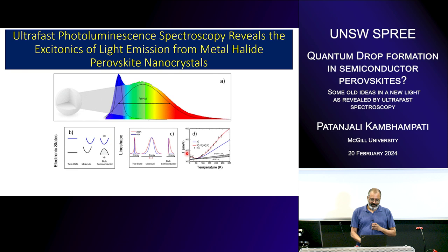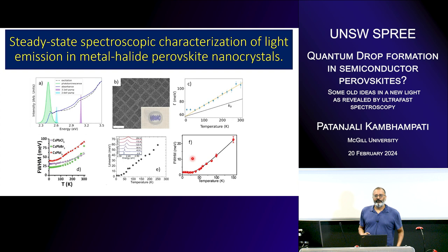So look at the slope and the offset. Here are a variety of cesium lead bromide nanocrystals. This data is from our group in an ensemble measurement, slope, offset. This data is from single particle measurements from another group, slope, offset. We always see this hockey stick shape, and the slope and the offset we aim to understand, and if we can understand it, then we can control it, ideally.